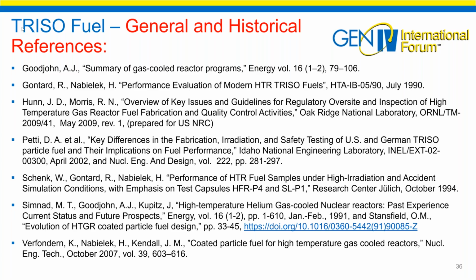Maybe if I were plutonium, I would. But let's say I want to make a ridiculously large particle. Okay, 500 microns. Let's say I wanted to make it 700 microns. Well, then the NRC would say, you've got a lot of fission products in there and you're going to use the same coating thicknesses. Prove it. So I would have to produce some sort of modeling to show I know what I'm doing with my physics. But more importantly, I would show that my statistics were there. But again, before I go to the Appendix B test, I would do some preliminary testing. For instance, X Energy is working on that, and we have others who are interested in doing that sort of proof test beforehand. So it might take about 5 years,